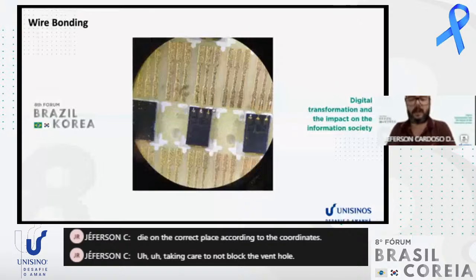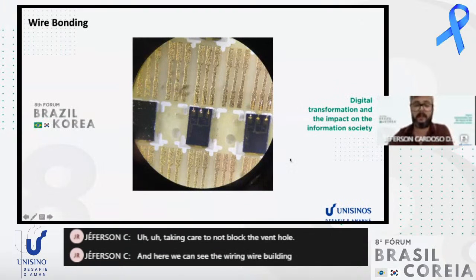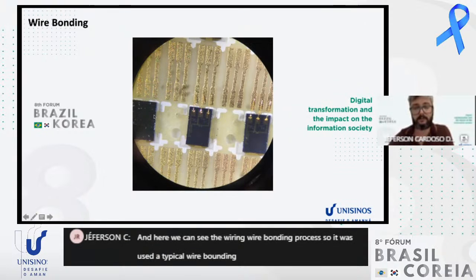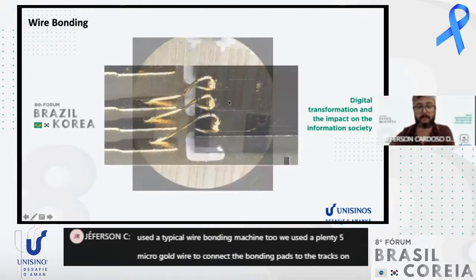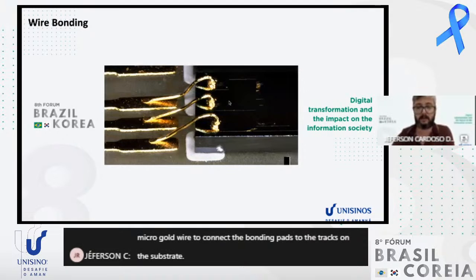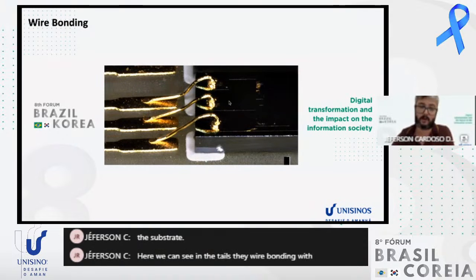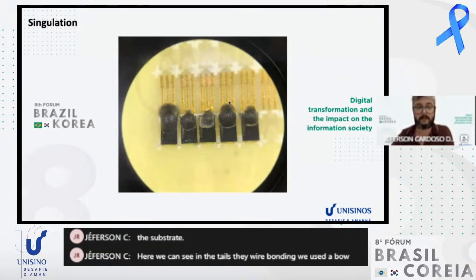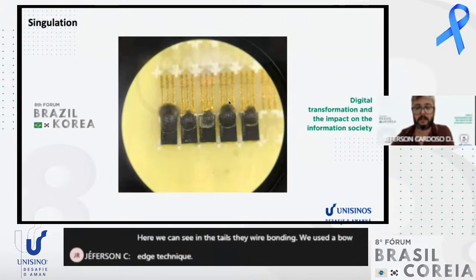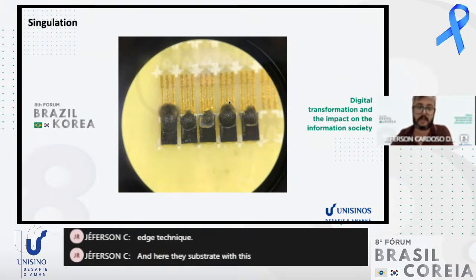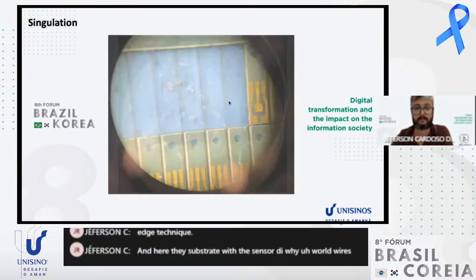And here we can see the wire bonding process. We used a typical wire bonding machine, with a 25 micron gold wire to connect the bonding pads to the tracks on the substrate. Here we can see in detail the wire bonding. We use the ball wedge technique. And here the substrate with the sensor die, gold wires, and protection for the wires.